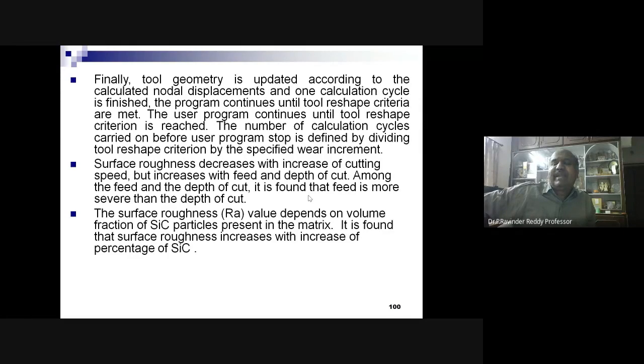The surface roughness decreases with increase of cutting speed, but increases with the feed and depth of cut. Among the feed and depth of cut, it is found that the feed is more severe than the depth of cut. The surface roughness value depends on the volume fraction of silicon carbide particulates present in the matrix.